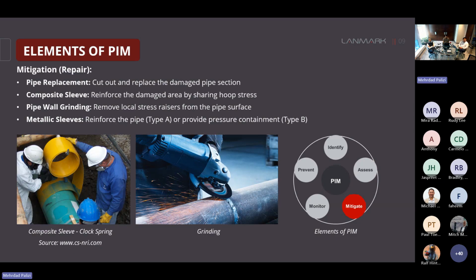Next, we have mitigation. This might be required when FFS is showing that an imperfection is unacceptable. After excavation and field inspection, if the defect was present and it was as severe as it shows itself in the ILI data, then a repair should be applied. There are different types of repairs depending on the type of defect and its severity. Common options include pipe replacement, composite sleeves, grinding, and metallic sleeves.